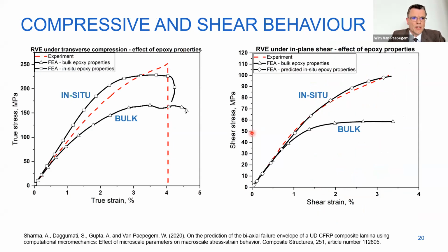If you look in the next slide, you see the stress strain curve for compression and in-plane shear. The red line is the experiment, and the black bottom line is the simulation with bulk epoxy properties. You see that we are quite far below the measured strength in shear and compression. If we adapt that to the in situ properties, which are higher because of an assumed size effect, you see that we come closer to the experimental one. I will come back to this also in the testing to show you some evidence of that.